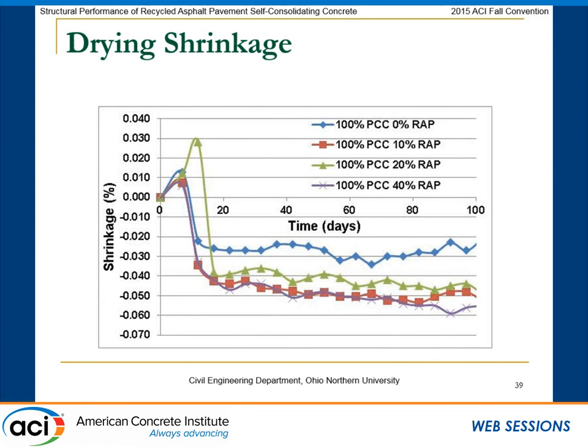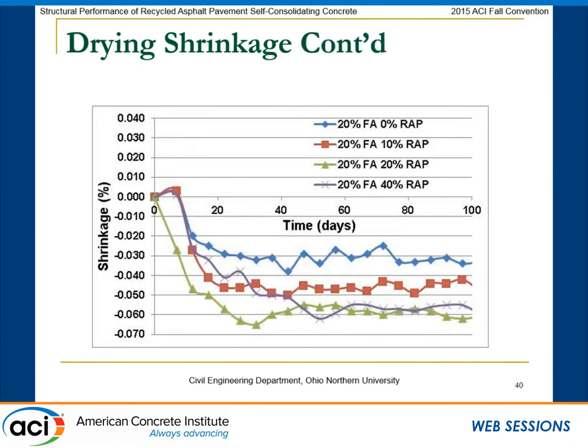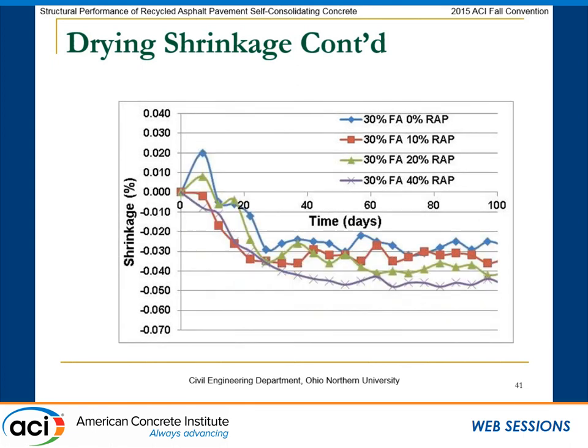So you can see here in general, as you increase the RAP content, as you saw in other presentations, your shrinkage increases. But actually, you can see maybe the 10% RAP did not follow this trend. But in general, this trend can be observed. You can see that trend also in the 20% fly ash. Maybe the 20% RAP here would be an exception. But also you can see here that you have higher strain. You have higher strain with the 20% fly ash.